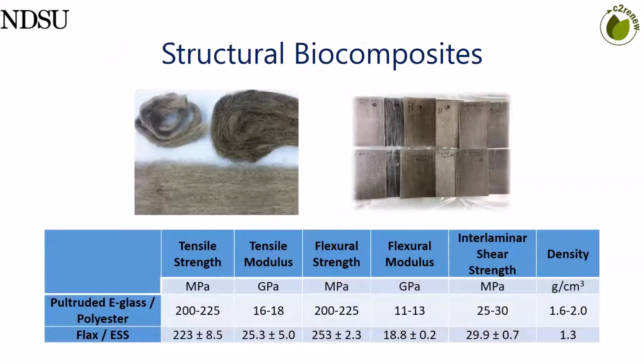Here's some data where we've gone head to head with a traditional pultruded E-glass and polyester composite versus a flax fiber reinforced epoxidized sucrose soyate type of resin. In that composite, we had 65% renewable based material. Between the flax and the resin, only some catalyst was petroleum based, so by and large we were at about 65% bio-based. We had properties on par, if not superior, to the petrochemical based pultruded E-glass and polyester, both in tensile and flexural properties,